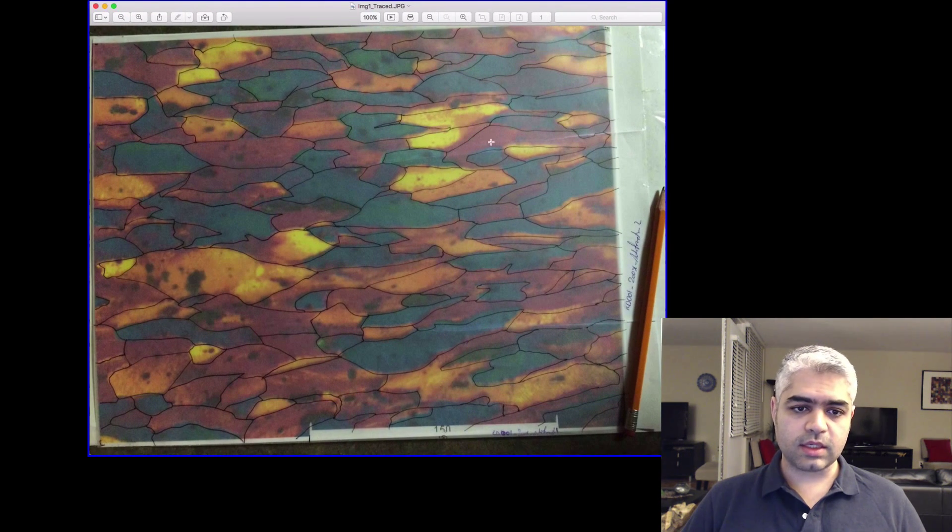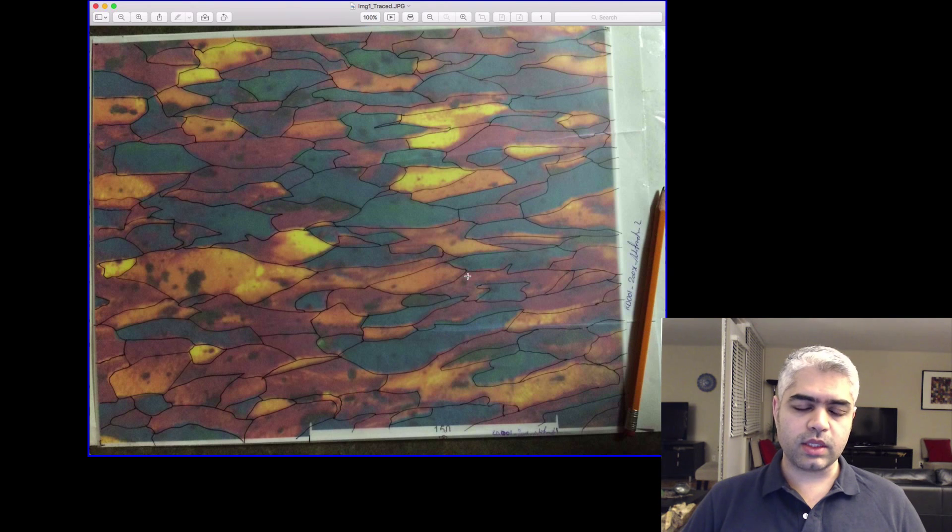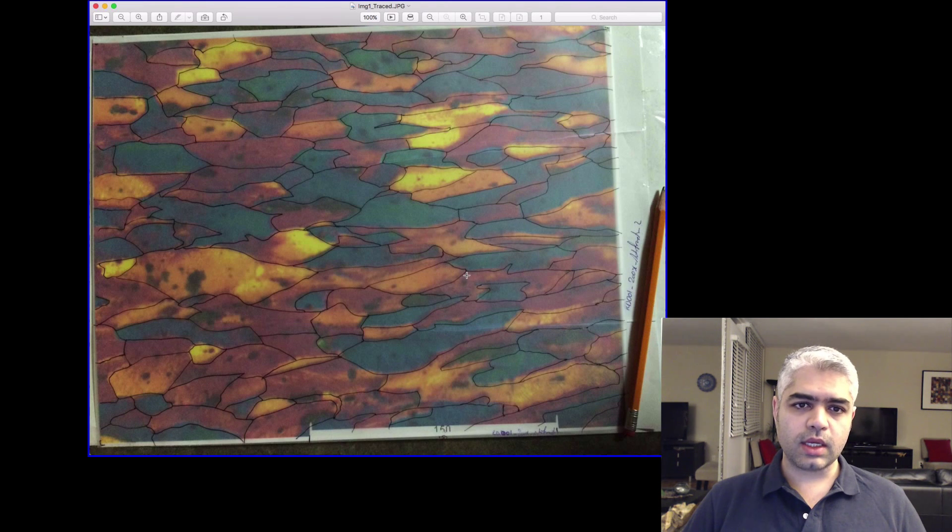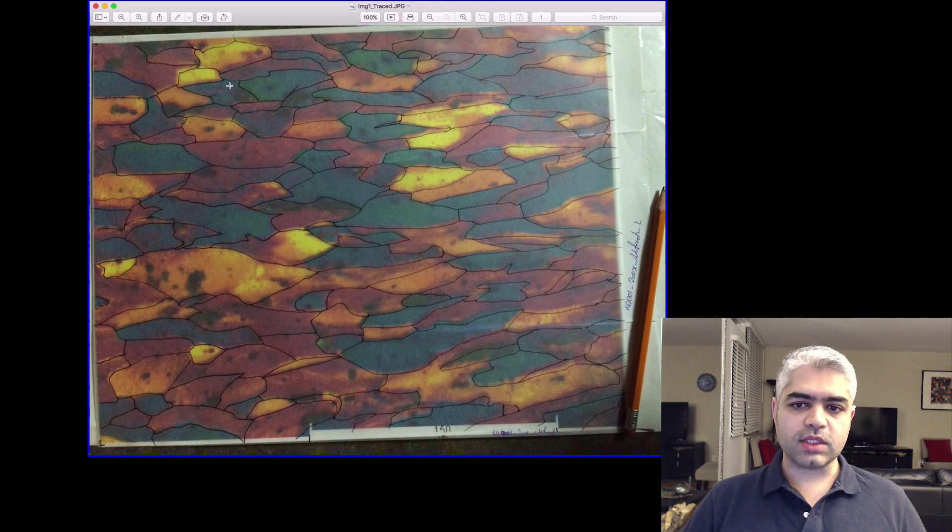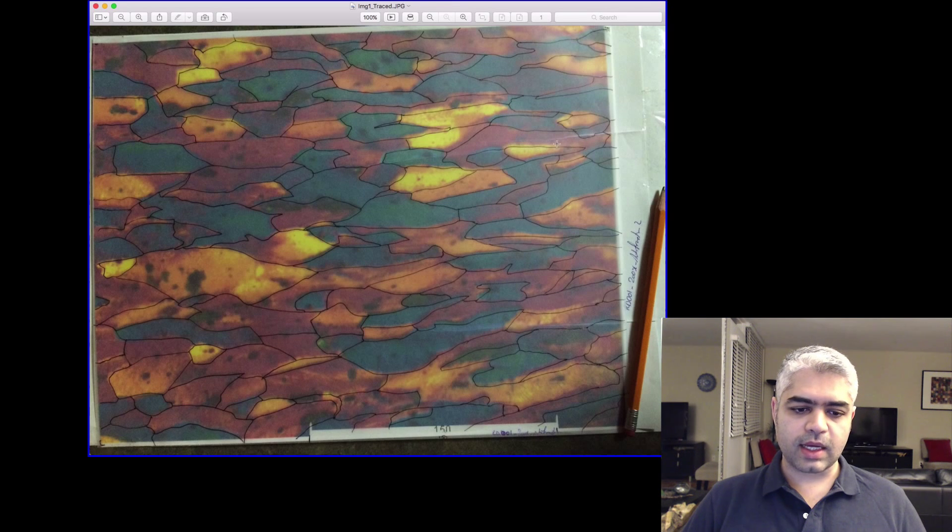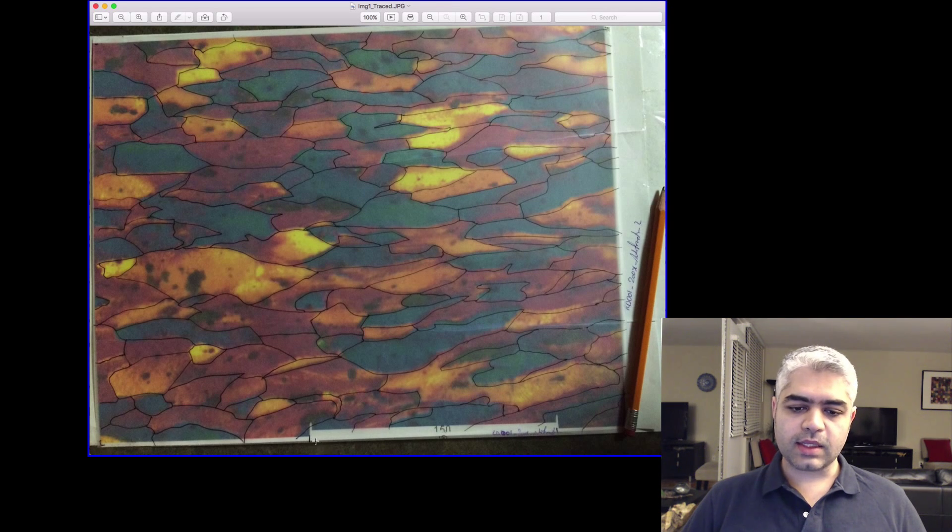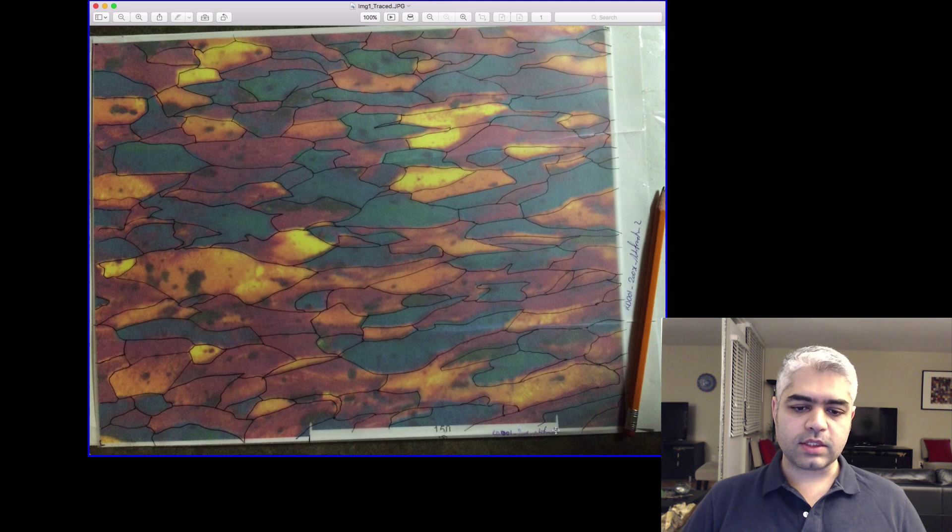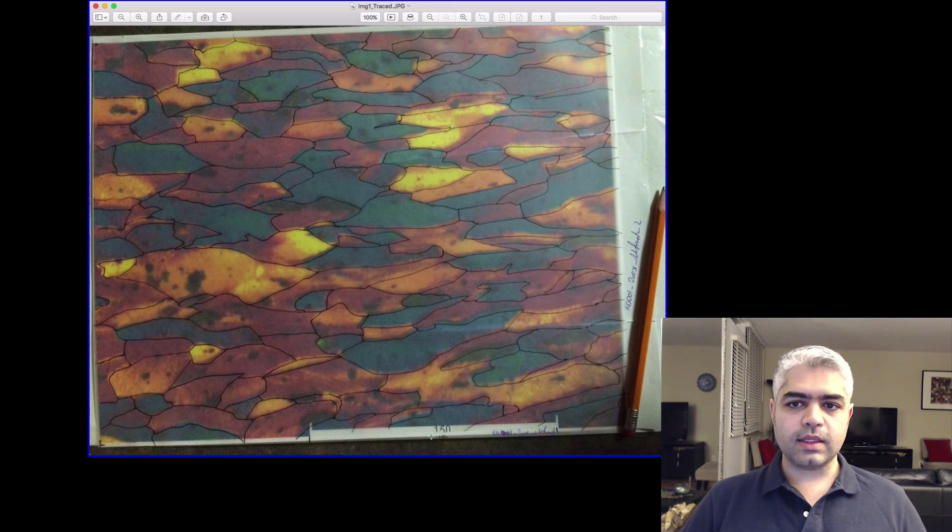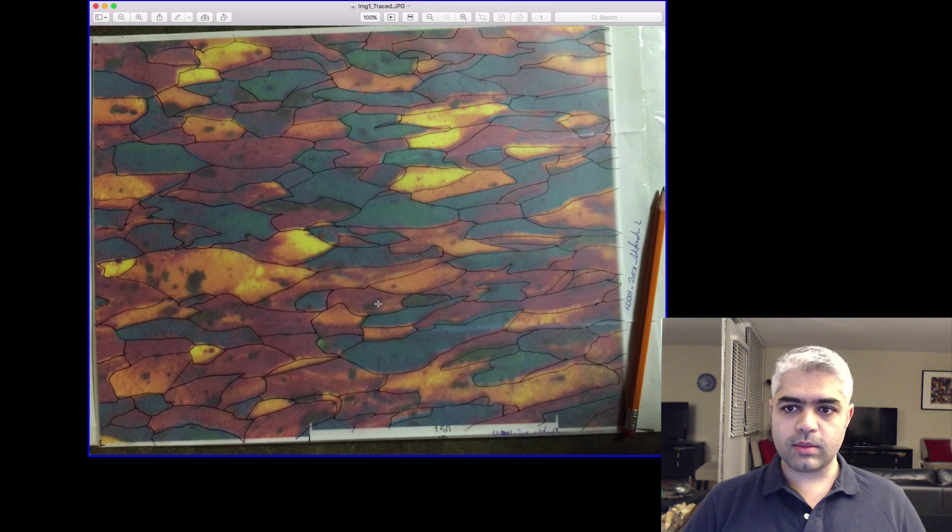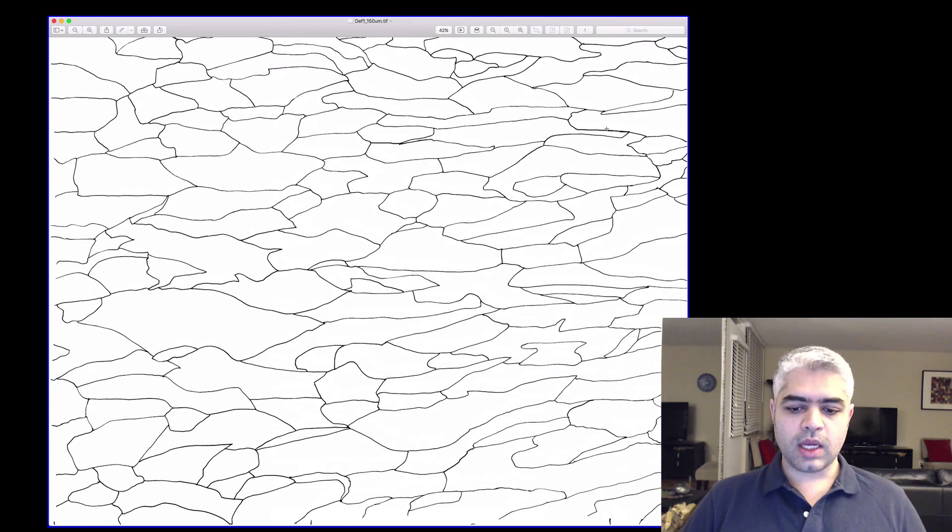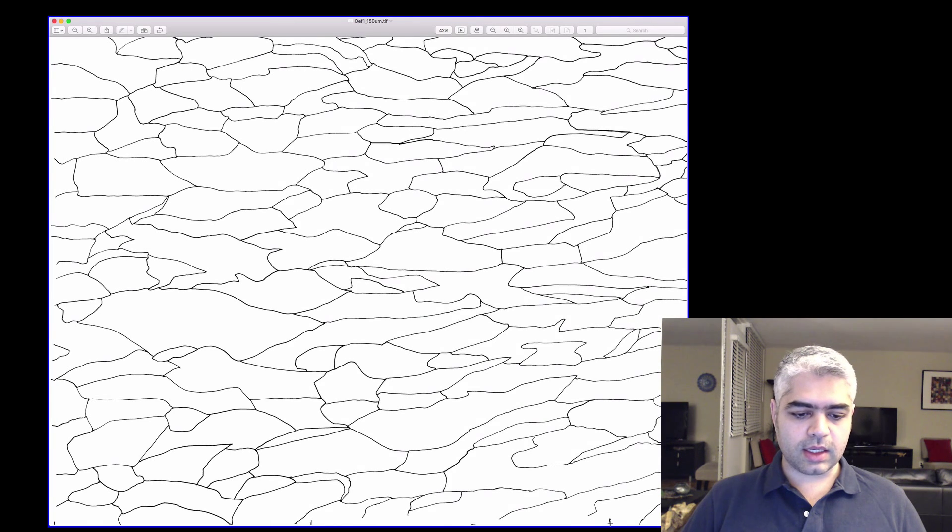Since my metallography was color metallography, I had difficulties with grain boundary detection with colored thresholding. So I ended up tracing the grain boundaries like this and marking the length and position of the scale bar as you can see here. Then I scanned this image and post-processed it a little bit.